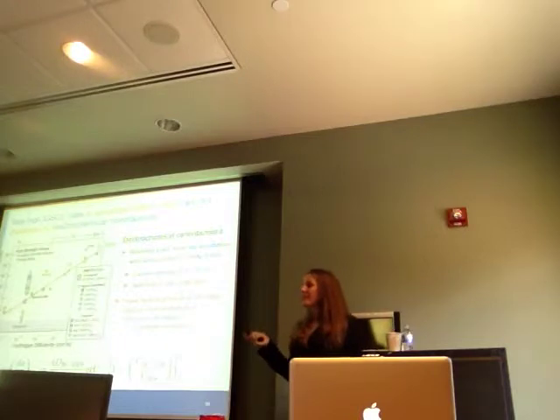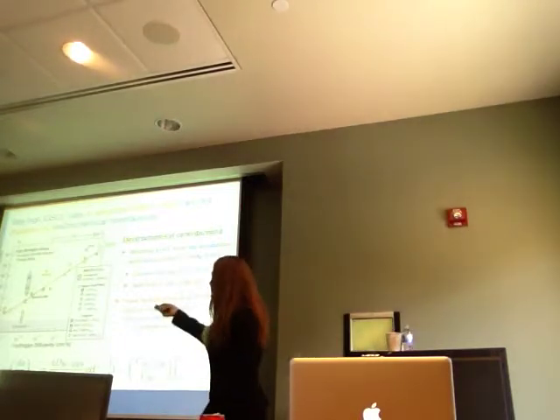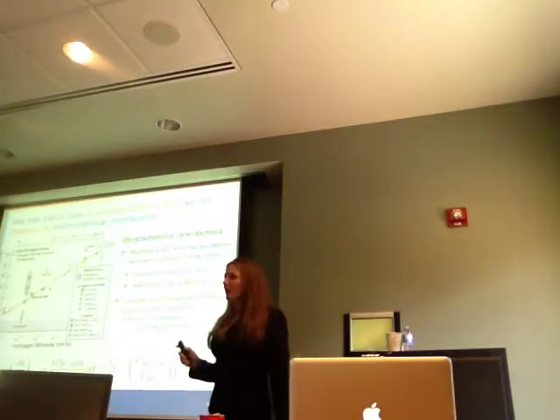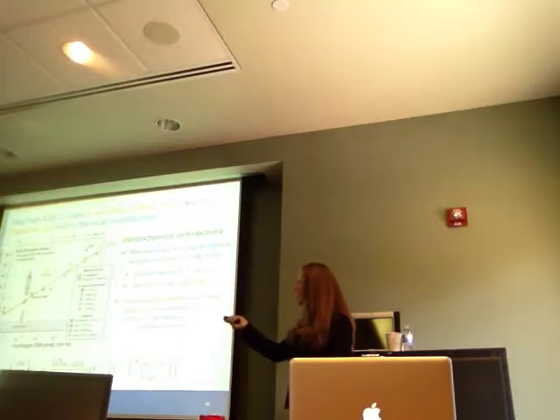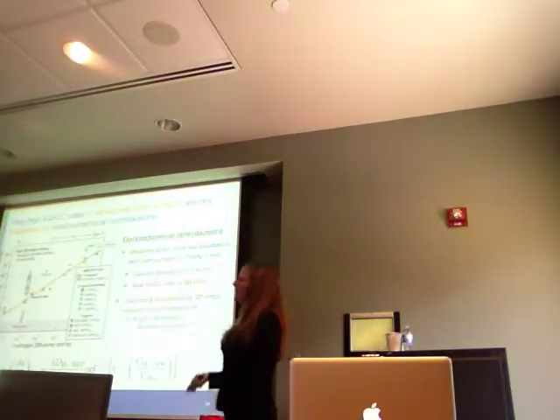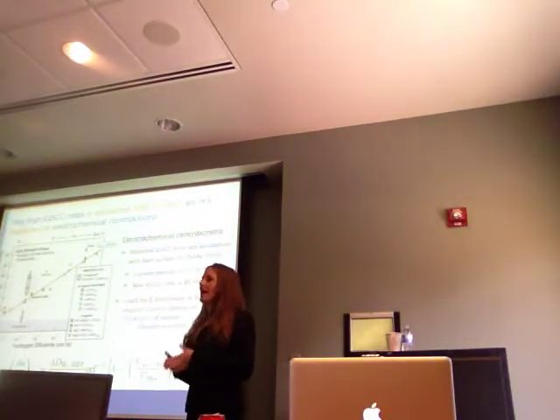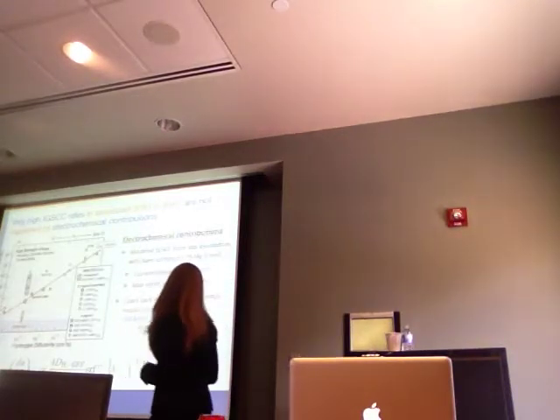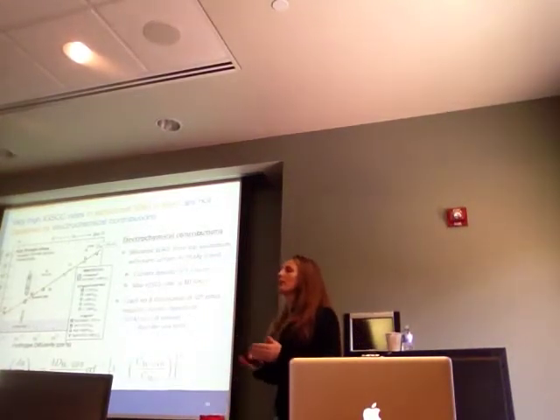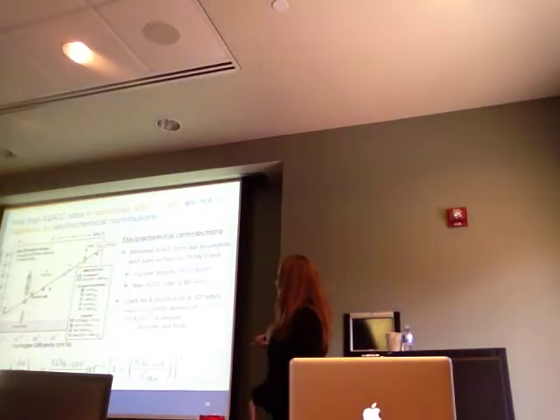If we wanted to look at the current density that would correlate with these crack growth rates, we would need 20 amps per centimeter squared. And you can't get that in the occluded crack tip because of your IR or ohmic drop limitation.